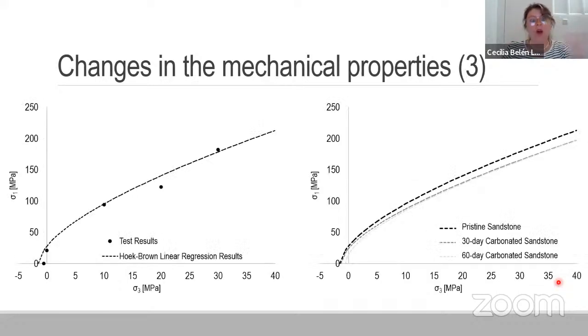With these mechanical properties obtained, we were able to obtain a Hoek-Brown linear regression, and we observed that as the amount of time in which the rock was exposed to CO2 increased, there was a reduction in the failure strength of the rock.